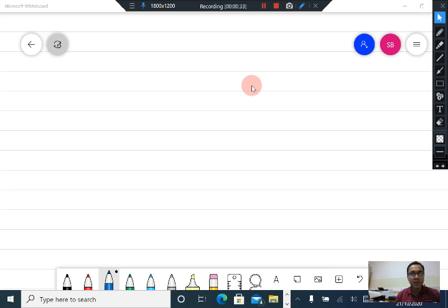of these two equations, where we had minimized the free energy with respect to the order parameter, which is taken as psi naught e raised to i phi. The order parameter psi is equal to psi naught e raised to i phi, where psi naught is proportional to the density of Cooper pairs inside the system, and phi is the phase. And we also minimize it with respect to the vector potential. When you do these two minimizations, one with respect to the vector potential and one with respect to the order parameter, you will land up with two GL equations.